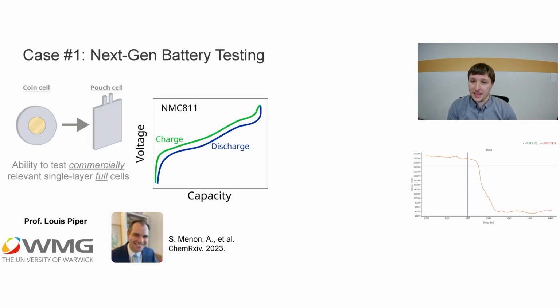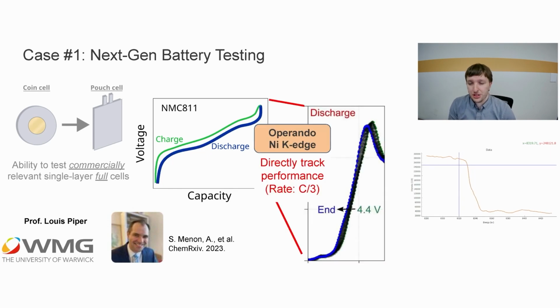In this case, they looked at the extended charge-discharge process of a commercially available battery cathode. XAFS was used to directly track the lithiation based on nickel reduction and oxidation. From this work, their group was able to gain new insights into the origin of lost performance during long-term cycling.